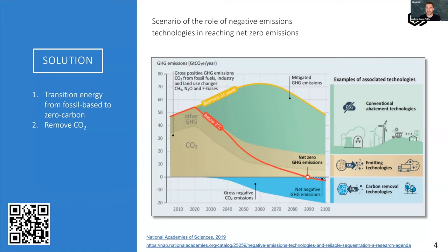If we then do a sensitivity analysis of all of the aspects of this particular approach, you can see that consistent with almost all commodity processing, selectivity, or in this case, carbon yield is the way to define that selectivity, is number one, the most important thing. We want a reactor that's retaining the maximum amount of carbon in the biomass into the char, just because that affects our overall yield and that affects the amount that we can take out of the air and permanently store. After that, it's biomass carbon content and moisture content. And after that, all of the other contributions to the cost are quite small. So that's why reactor performance and the novelty and intellectual property that we have in our reactor is so important for the performance here of this particular system.